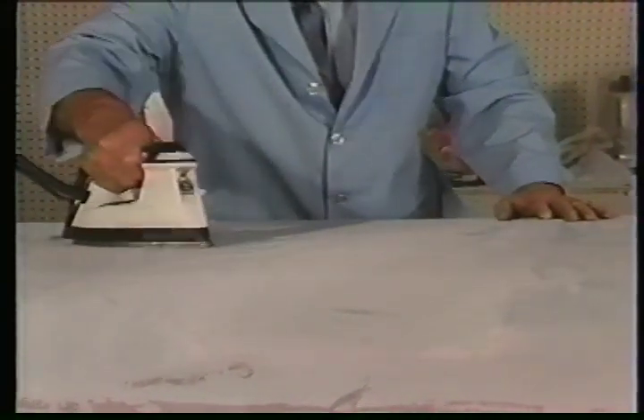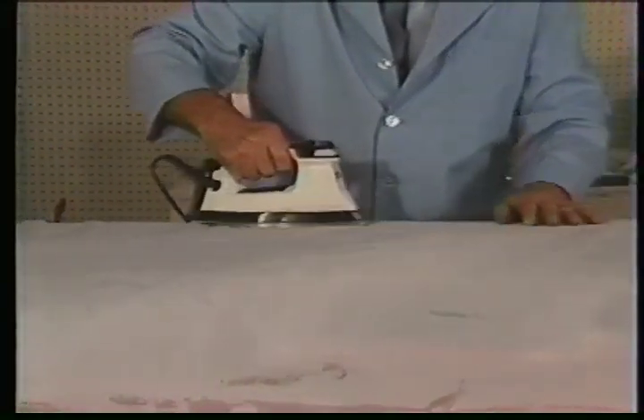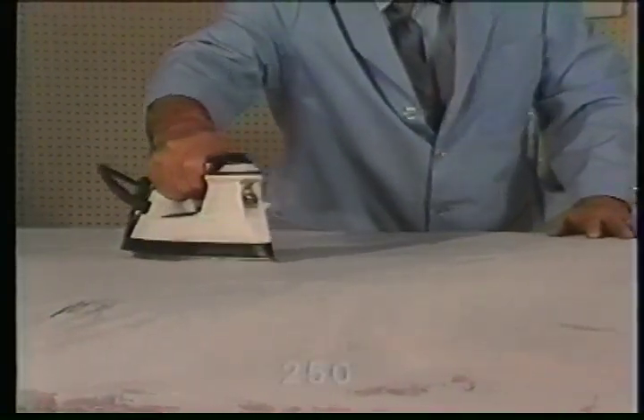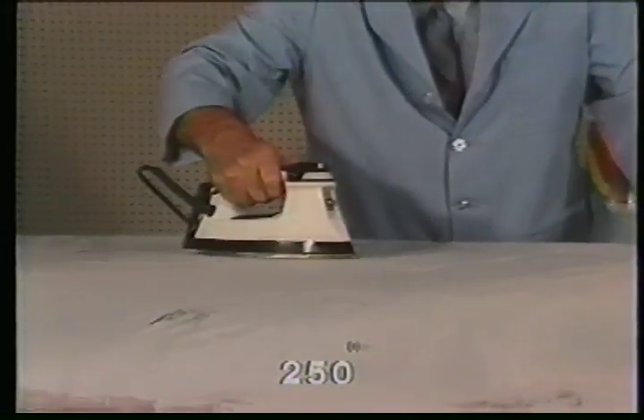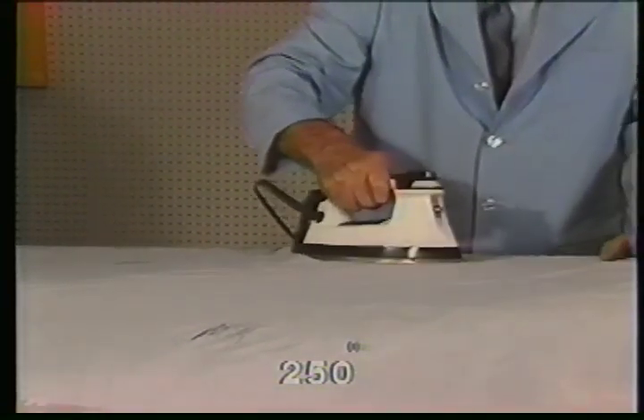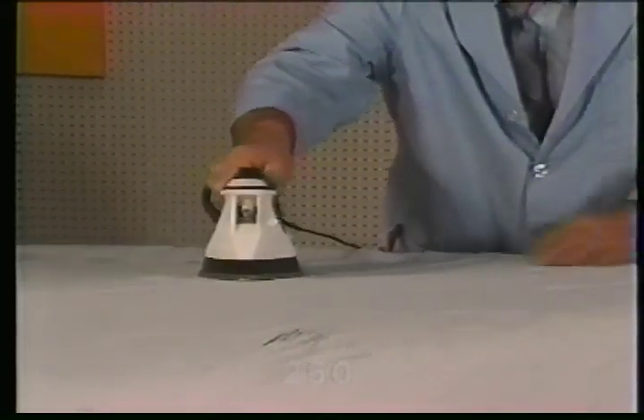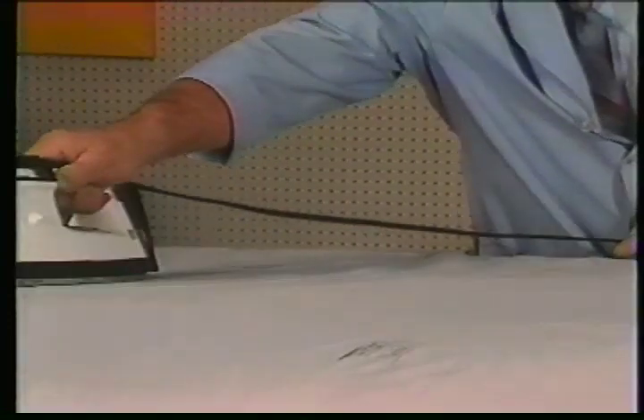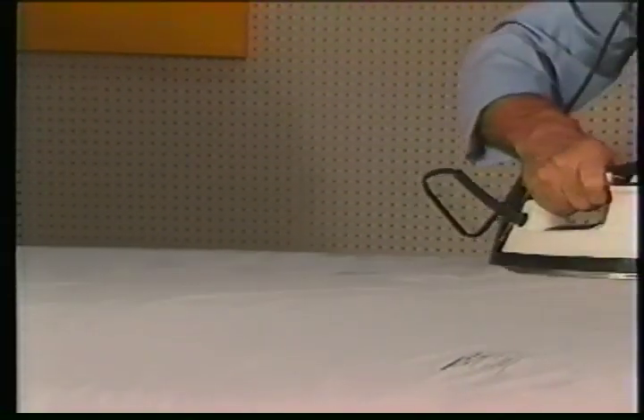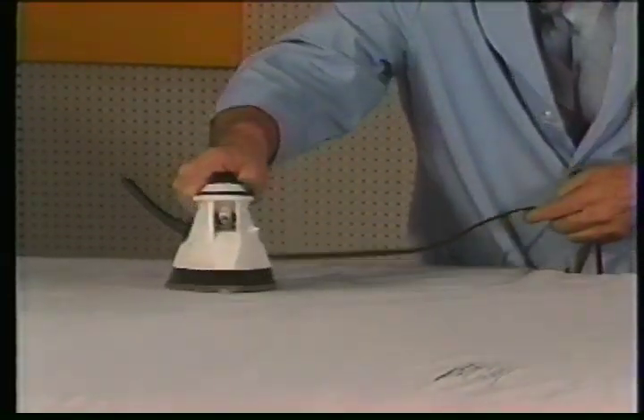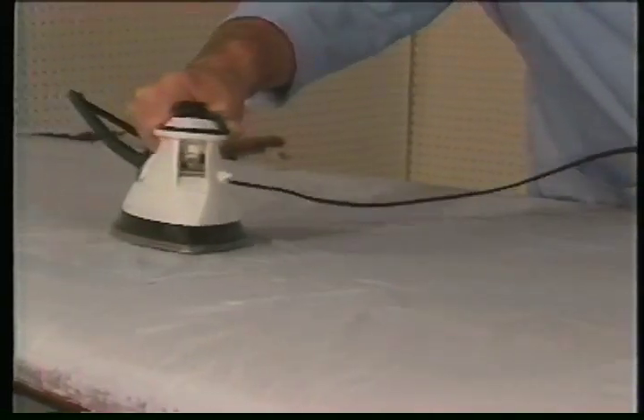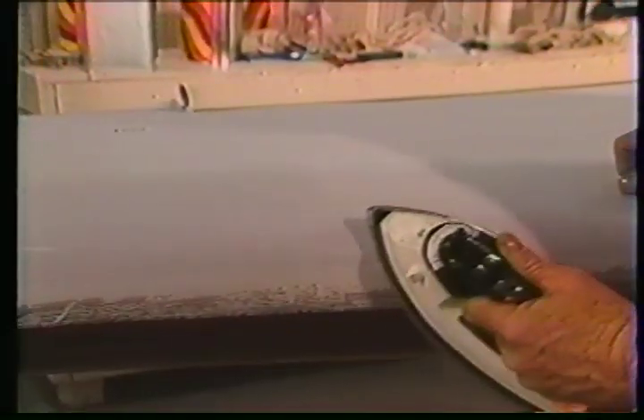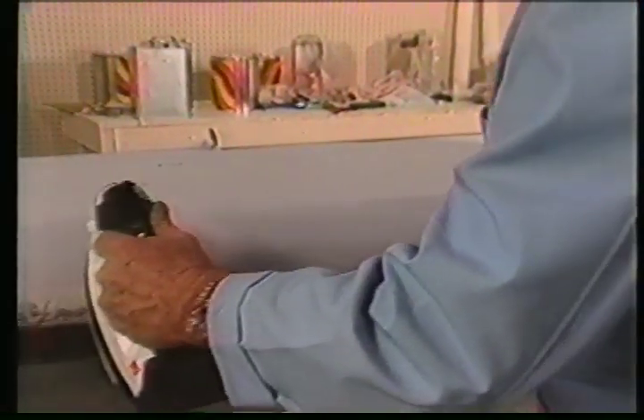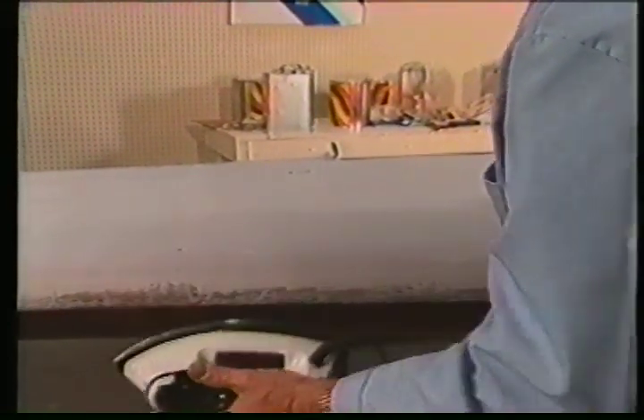The heat shrinking procedure for polyester fabric over plywood is different than open panel areas. The iron is used at 250 degrees to remove fold creases and wrinkles which will show through the finish coat. Full fabric tension at 350 degrees is not used because it will bridge or pull fabric out of any shallow low areas of old warped plywood components. The plywood heat sink under the fabric requires slower movement of the iron to heat the fabric. After fold creases and wrinkles are removed, the surface is ready for the first coat of polybrush.